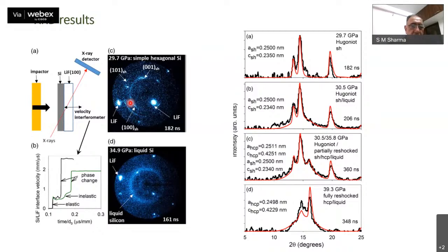And it's also often assumed that the cubic to beta-tin phase transformation, because it's first order and has a very large volume change, is what we call reconstructive, that it breaks the bonds and rebuilds them. It's because the cubic phase is diamond structured, with very clearly oriented directional bonds, while the beta-tin is a metallic phase. So it's a lot more, should I say, electron states are delocalized. So it doesn't have those directional bonds per se.